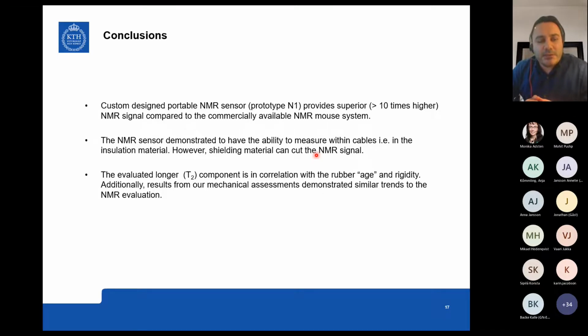As I also mentioned, the transverse relaxation times that we are measuring with the cable, with this device, they're rather short compared to ordinary polymers that we've been working with before. So we've essentially devised a way of quickly, based on the curves that we acquire, to analyze what is the aged polymer contribution, what is essentially from the oil extender in the polymer. So we can quickly just single out what is what from the data.